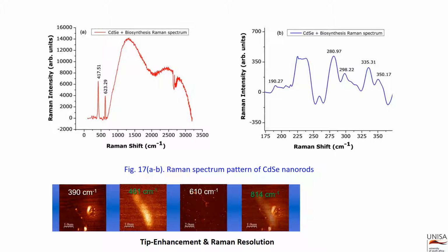The deconvoluted bands of cadmium selenide in figure 17B were observed at 190 centimeter inverse, 225 centimeter inverse, 259, 280, 298, 335, 350, 417, and 623 centimeter inverse. It is also pointed out that these bands are much more enhanced with laser excitations of 632 nanometers and the UV at 325 nanometers respectively.